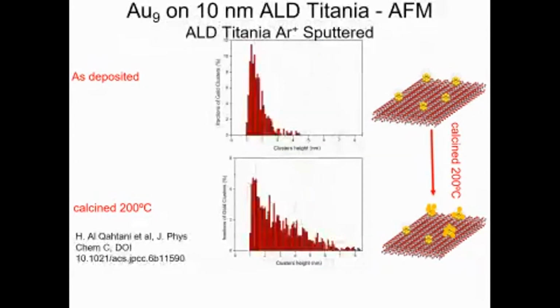We also use atomic layer deposition, which gives a very thin titania deposit on the substrate, with a thickness of 10 nanometers. And we study this nanocluster aggregation and the degree of aggregation on different titanium oxides. We tried the nanosheet, we tried P25, and now we tried atomic layer deposition. And we sputter this to create what's called oxygen defects on the substrate itself.